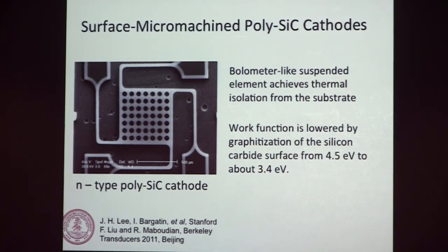Interesting things happen with work functions. It's very much a surface phenomenon. Silicon carbide has a work function of 4.5, but in operation, this device shows a work function of 3.4, which is much closer to what you get in graphite. And so the surface may actually be transforming.